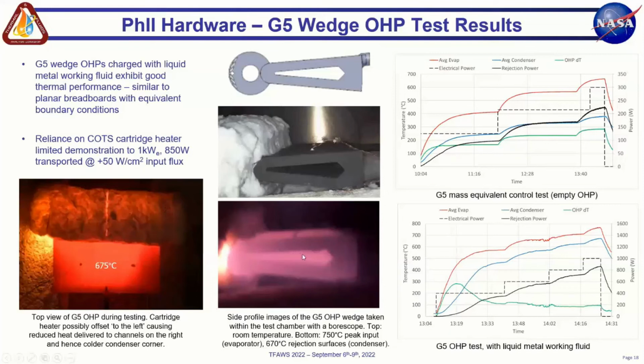We have a variety of pictures here. The lower one is a borescope inside of our argon purged box. Here's a top view through the viewport. We were able to drive this part, made by a powder-based additive manufacturing method in Inconel, up to 675 at the condenser surface. And we ran the exact same part vented of a working fluid, with that time series data shown in the top here, where you can see approximately an order of magnitude increase in the conductance of the OHP as opposed to the mass equivalent Inconel structure. It's just vented as our favorite control.